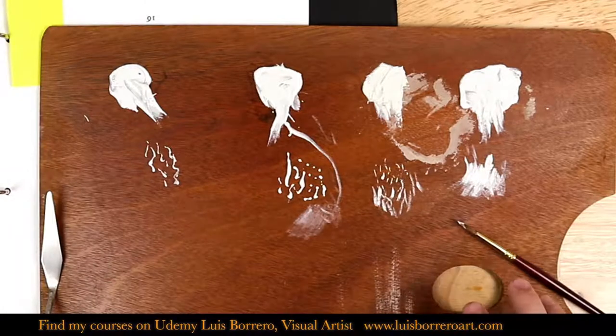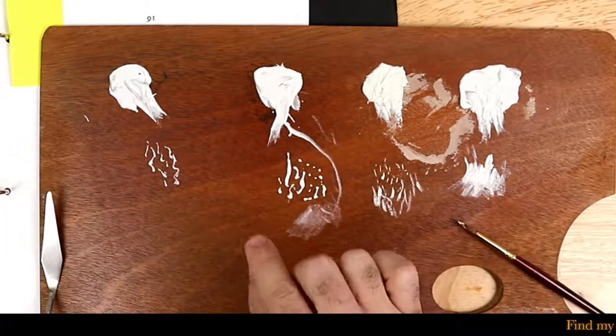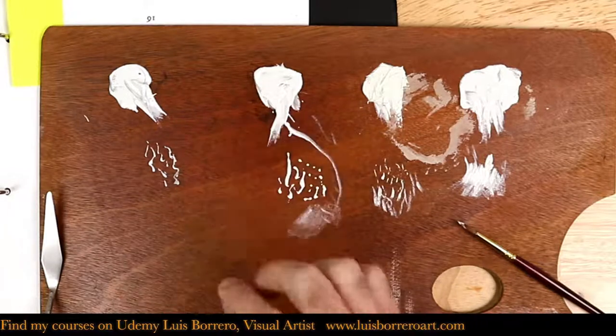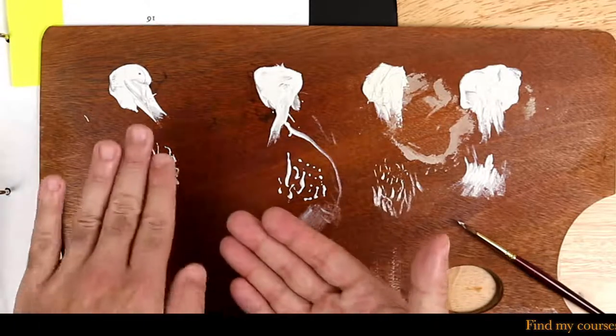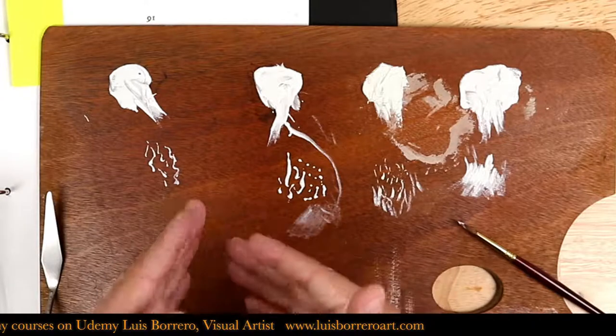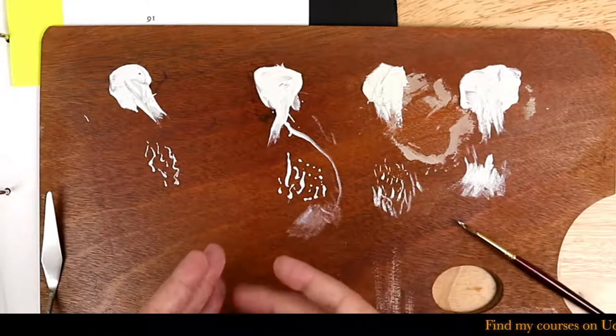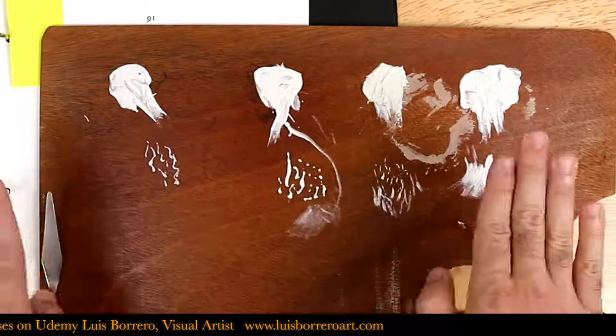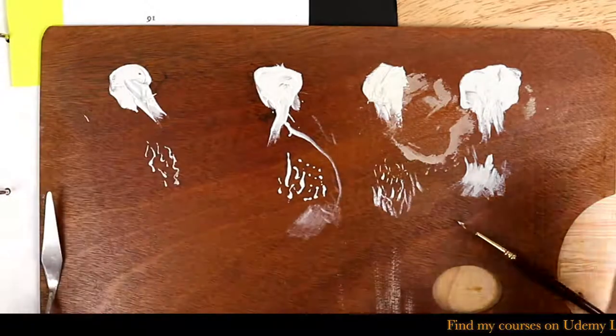Now, this is very interesting, Ron, because they have found tempera repaintings in most of Caravaggio's works, and why would Caravaggio be retouching his oil paintings with tempera, meaning stack processed lead white mixed with the tempera medium? Well, the reason is because if this lead white is mixed with tempera, it will be so much whiter. The linseed oil is actually degrading the color. Now, by grinding the color even more, you could improve that quality. That's the reason that this is a half hour grind versus an hour grind. So you get a full range. But by grinding the pigment a lot finer, you get a whiter white.